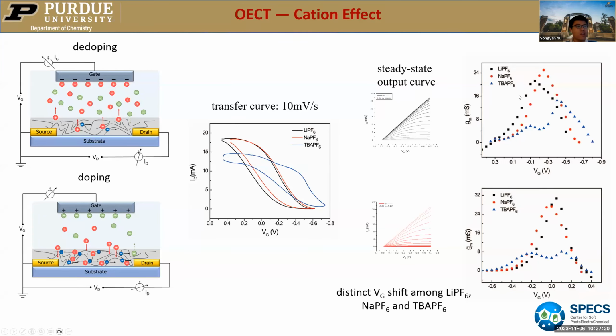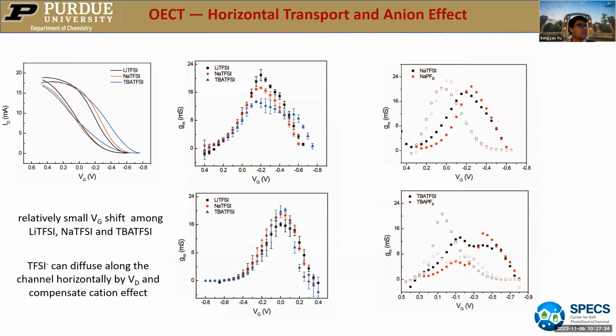For the de-doping process, we can see lithium is the easiest for de-doping, sodium is second, TBA is third. And in the doping process, it's reversed. So there's a distinct VG shift among these three electrolytes. When we change to lithium, sodium and TBA TFSI, it's kind of different. In their transconductance plot, their separation, even though I tried many times and even made an error bar here, is not as large as the PF6 plot.